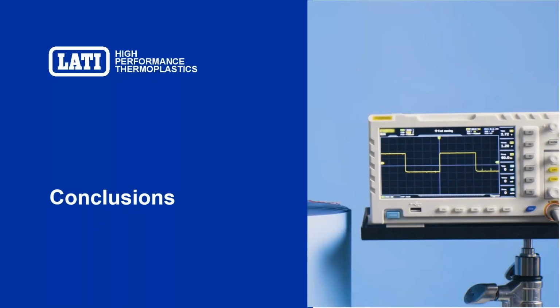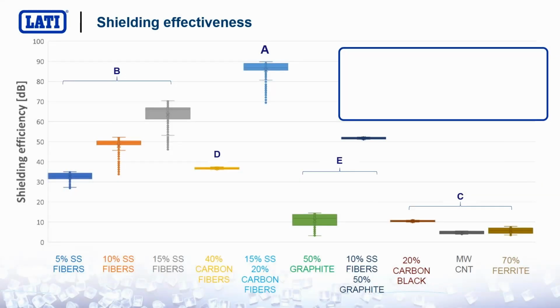Now, some conclusions. We put on this graph the shielding effectiveness at 1.5 millimeter of all the compounds that we tested. The results are evident. The steel and carbon mixture performed much better than all the others. So we had the maximum shielding efficiency at the lowest thickness using the stainless steel plus carbon fiber compound.